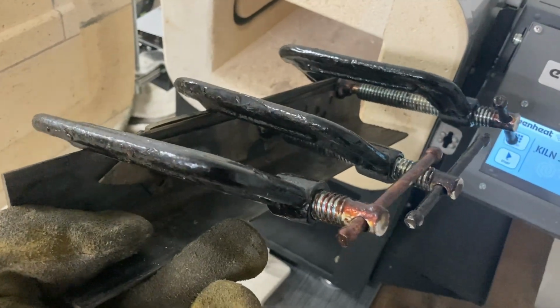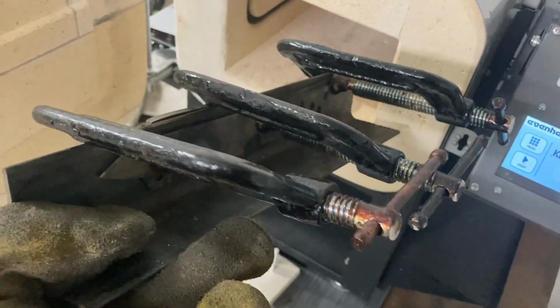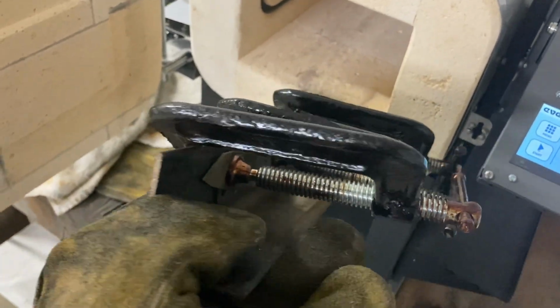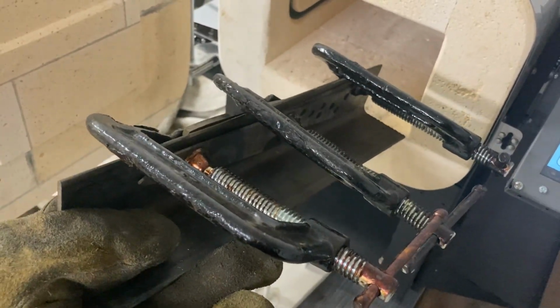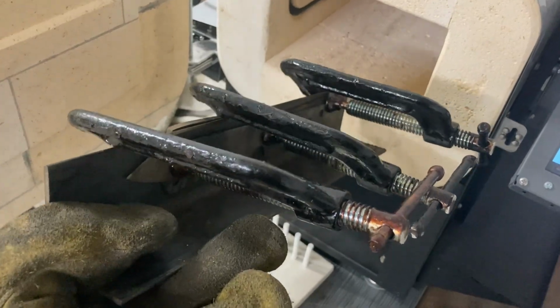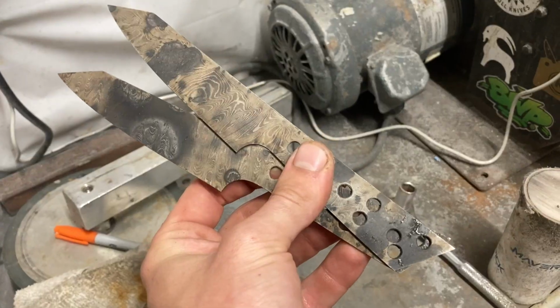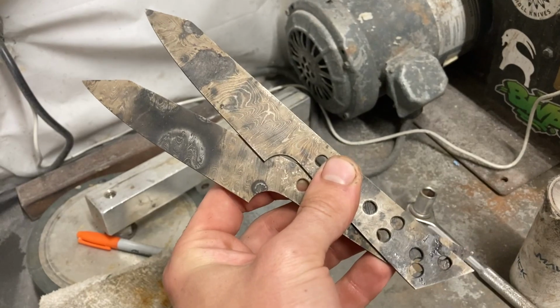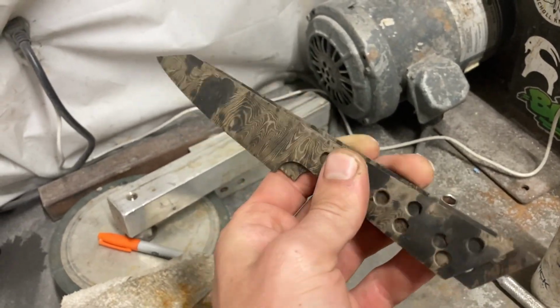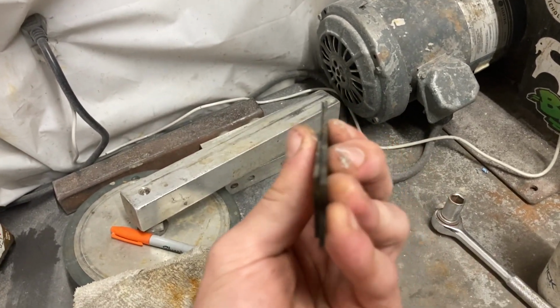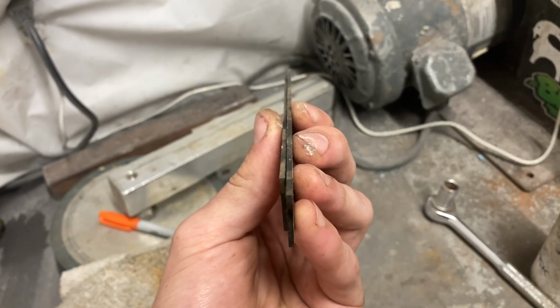The blades are slightly warped out of quench, so I just put them in my little straightening jig, which is a piece of angle iron with some clamps, and then I tempered them twice for 2 hours each at 400 degrees. Here's what they look like after the whole heat treating process. They have a nice straw gold color and are pretty nice and straight, and any little bit of warp now I'll be able to take out when I'm grinding them.